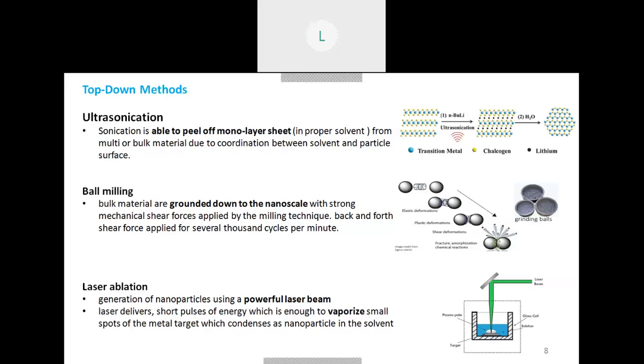The ball milling, where the various metallic balls apply the shear force on several materials so that they can be lowered down to the nanoscales. But the problem with the ball milling is that there can be huge contaminations. The laser ablation also, we apply huge powerful laser beams which vaporize the material first, and then it gets condensed in the proper solvent or aqueous form into the nanoparticles. Again, the laser ablation requires huge electricity. That is the disadvantage of it.